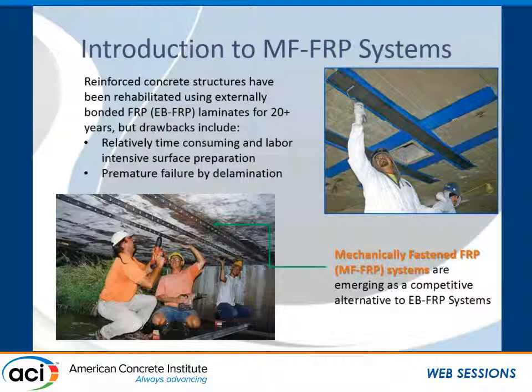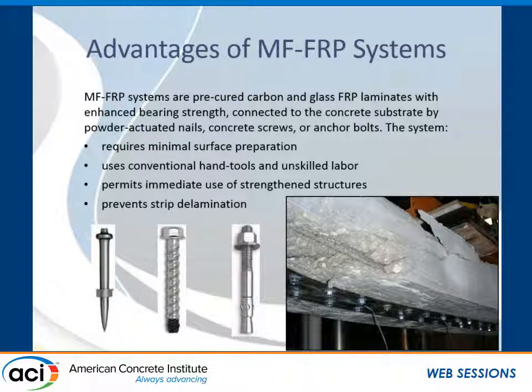Mechanically fastened FRP systems, which do not require bonding, provide an alternate strengthening method. In fact, they were first used by the military for rapid strengthening of bridges. The MF-FRP systems consist of pre-cured FRP laminates that are connected to the concrete substrate with concrete screws, nails, or anchor bolts. For successful applications, the chosen FRP laminates, which are typically hybrids of carbon and glass fibers, must have enhanced bearing strength to support the load transfer that takes place through the fasteners. The installation method requires minimal surface preparation, uses conventional hand tools and unskilled labor. MF-FRP systems provide comparable strength increase while avoiding the brittle delamination failure common with the externally bonded systems.